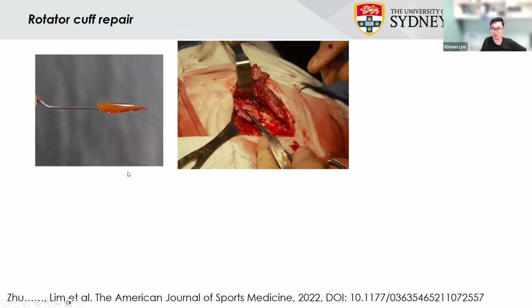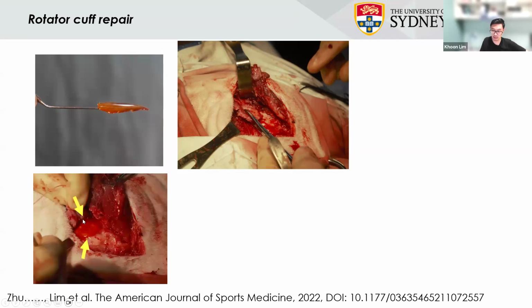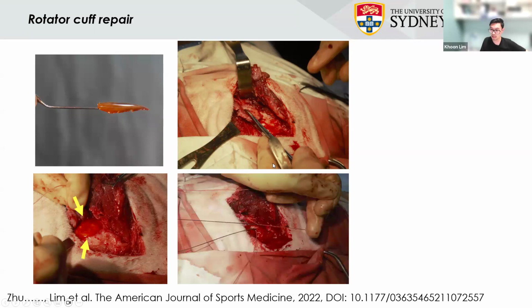So one thing that we did was for rotator cuff repair. So this is one of the PVA tyramine hydrogel that we added with a cocktail of growth factor. This is a sheep acute rotator cuff surgery. This is where the cuff is. This is where the surgeons then put on our hydrogel, suture it in. You can see that here.